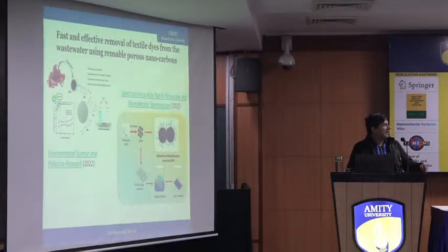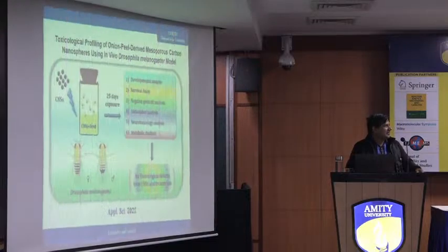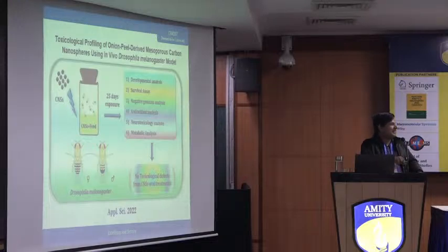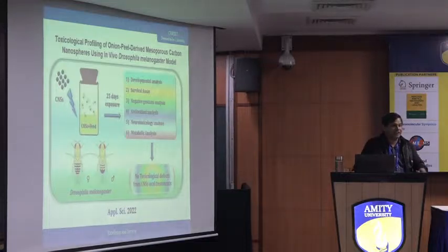Then again, for water purification, you can see within 30 seconds, we are able to purify all the contaminated water. And this is another interesting application, with the Drosophila melanogaster insect. The idea was to feed this nanoparticle to these insects and see how many days they can survive. But to our surprise, whenever we fed our nanoparticle, instead of dying, the insect starts growing. So it's another application, because it's completely non-toxic. Actually, the insects are enjoying these nanoparticles. So indirectly we can create systems with a non-toxic approach for applications.